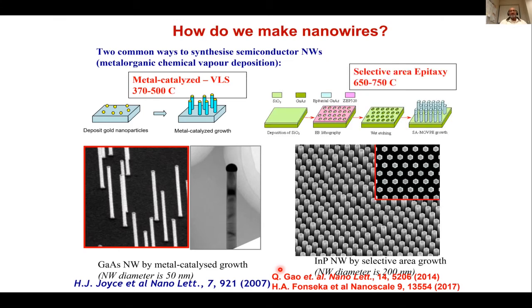There are two main techniques which we use. One is called the metal-catalyzed VLS growth process, which I'll come back to, and the other technique is called selective area epitaxy. And we use a technique called metal organic chemical vapor deposition, or MOCVD. There's also an alternative technique called molecular beam epitaxy. And you can choose whichever technique is accessible to you in order to make these nanowires.